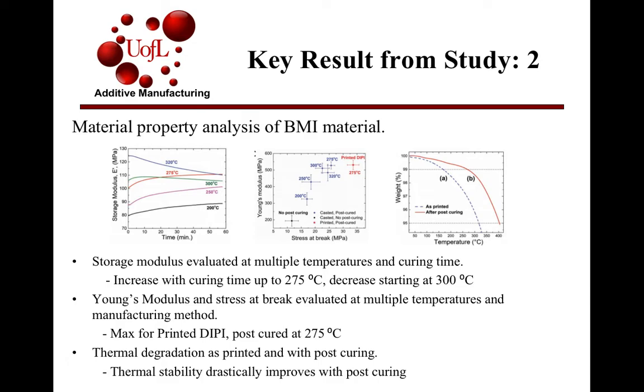The second material property the researchers analyzed was the Young's modulus and the stress at break. They evaluated these at multiple temperatures and different manufacturing methods, and were able to confirm that the max Young's modulus was for printed DIPI ink post-cured at a temperature of 275 degrees, which is shown in the top right of that Young's modulus graph there in red, where all the other points are shown in blue.